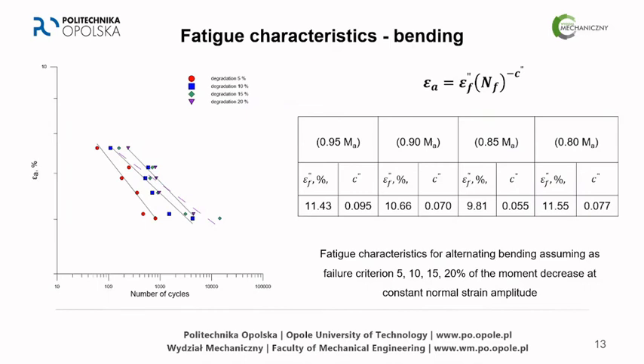Right here you can see that we have another graph, and they were presented in such a way that for basic characteristic points we prepared sets of data. For example, for degradation equal to 5%, for all of those 6 curves which are presented like on the previous slide. So for degradation 5%, 10%, 15 and 20, we prepared curves which have a dependence of strain as a function of number of cycles. And then the fatigue characteristics based on it were prepared. As you may see, in this case, the degradation 5 and 10 and 15% were parallel to each other.